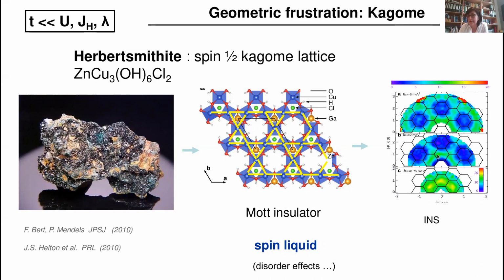It shows these very diffuse inelastic neutron scattering patterns. However, these materials are prone to disorder effects, so there is still a lot of discussion about the observation, or not, of spin liquid behavior and the corresponding fractionalized excitations in this system.